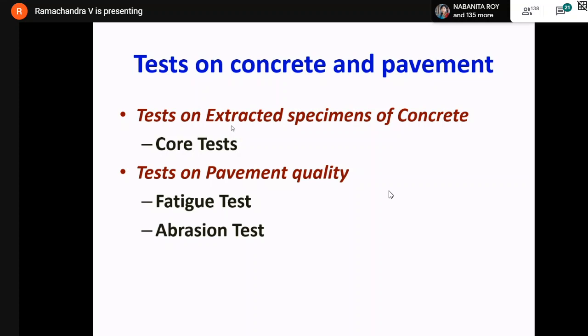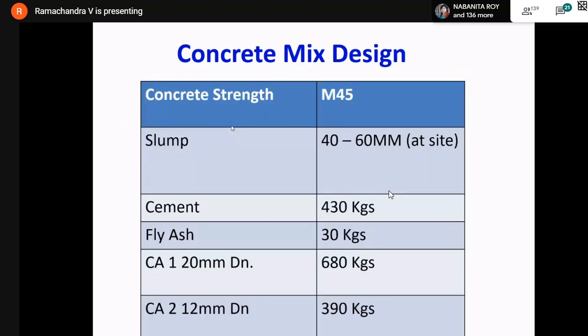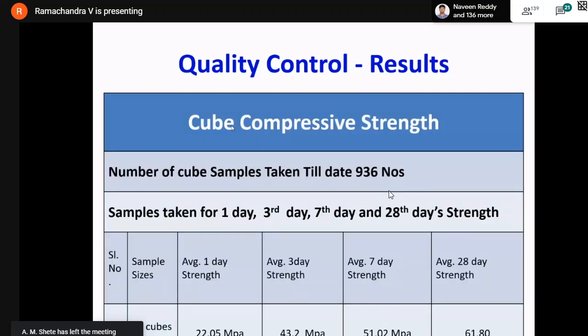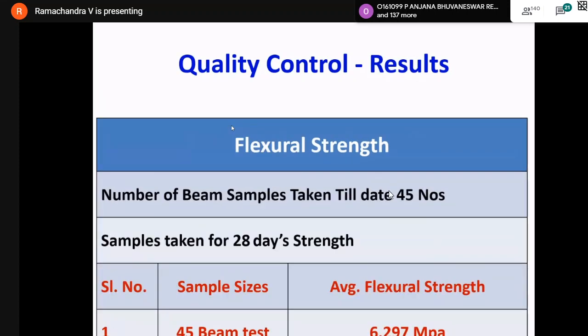Now, this is the typical mix design of concrete. How many kgs of cement per meter cube of concrete and so on. These are the compressive strengths for a particular project. Flexural strength was more than 6.2 MPa. What is required is 4.5 MPa.